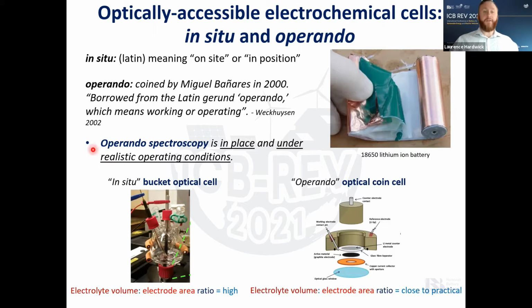In terms of defining whether we've done an in situ experiment or an operando experiment, I like to define it a little bit more specifically to our activity. Whenever we use glass cells, where the electrolyte to electrode area ratio is high, so we have a significant electrolyte volume, I call this an in situ experiment. And when we've used a specialized cell, with a coin cell geometry in which we have an optical window to access the electrode whilst it's under operating conditions, I define this as an operando experiment. Here the electrolyte to electrode area ratio is coming closer to what you'd get in a practical lithium-ion cell.